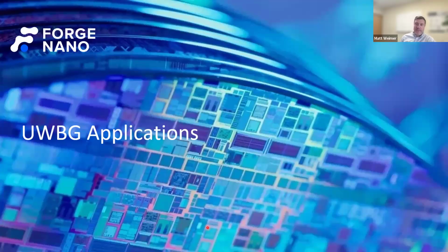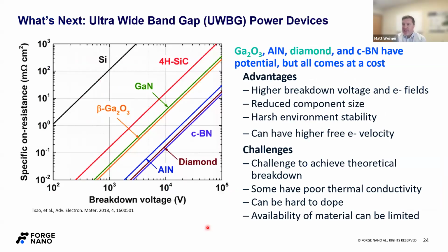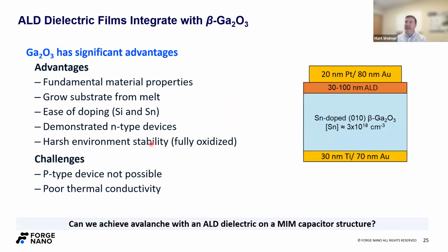All right, let's spend maybe the last 10 minutes or so talking about ultra wide bandgap applications. So this is a slide I showed earlier. In the interest of time, I'm not going to go over it again, but let's just briefly mention that the point here is you have these higher breakdown fields at a given on resistance. But it's really hard to achieve those, practically speaking, when you're building a device. So this is where we really feel like ALD can make an impact. And we wanted to start with beta gallium oxide. It seems from our reading of the literature that this is a place that Mother Nature's kind of playing nice with us, right? There's not too many problems between the ALD and the gallium oxide.